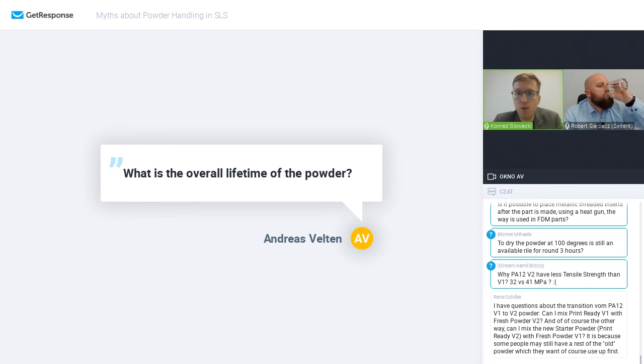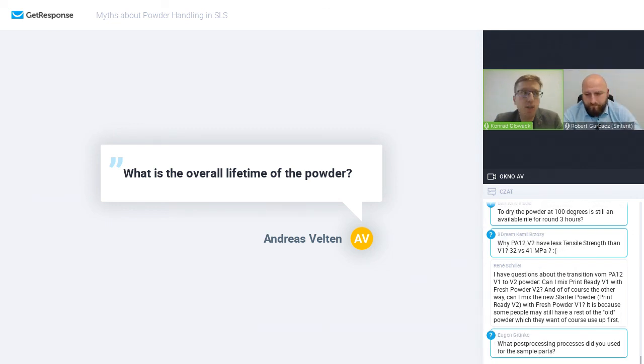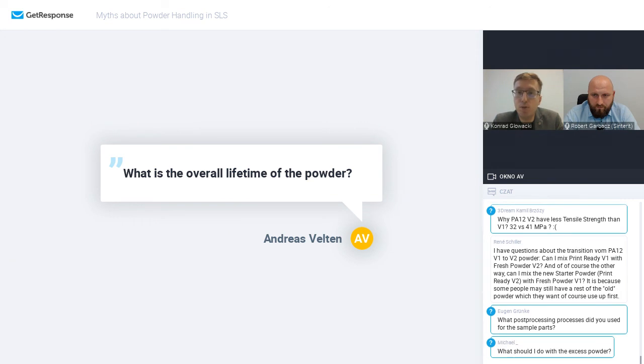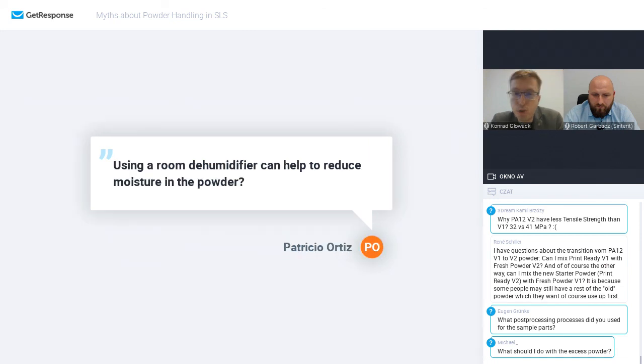So when properly mixed, it should be working continuously. Right now we give 12 months shelf life of the powder, but when you mix in the fresh powder, we haven't found any issue with that. If you continuously print at least once a month, there should be no problem with the lifetime of the powder. It will just keep being reused and reused. Thank you, Andreas, for the question.